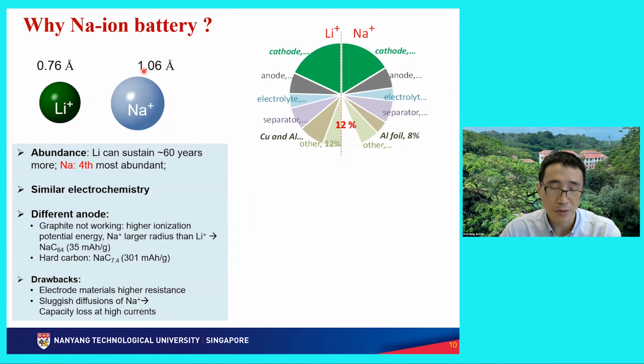But then if you look at more detailed electrochemistry, the first concern is that the ionic radius is larger: 0.76 angstrom for lithium, 1.06 angstrom for sodium. A larger ionic radius means that in the lattice of the crystals, it's not so easy to diffuse in and out, right? So diffusion becomes more sluggish. But the good thing is that it is abundant. And the electrochemistry of the battery mechanism is quite similar, almost the same as the lithium battery, although the materials are different. Both positive and negative materials are different, but the electrochemical working mechanism is basically the same. So people can learn a lot from the dominating lithium batteries' electrochemistry.